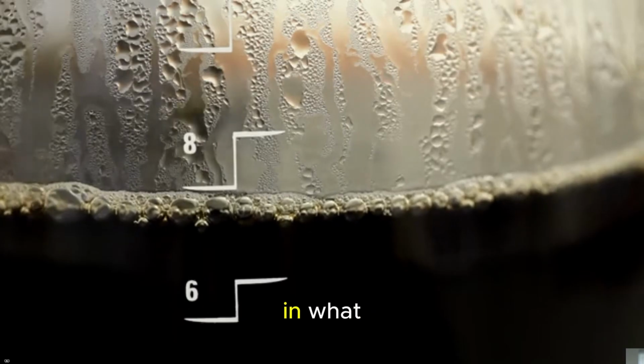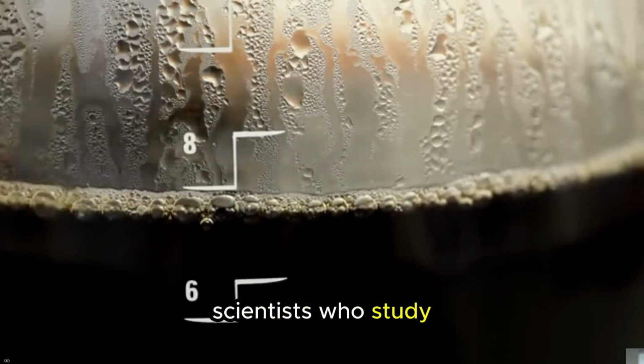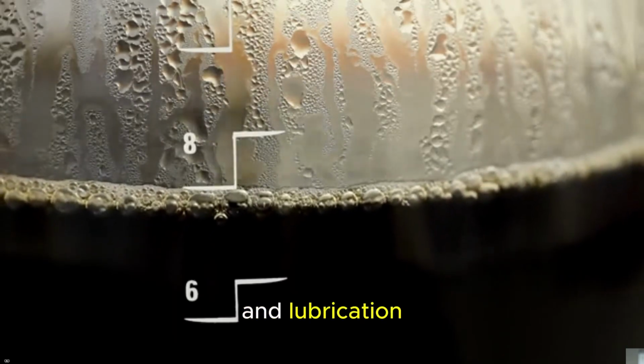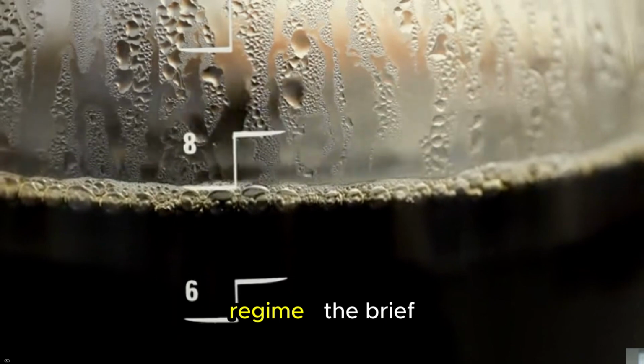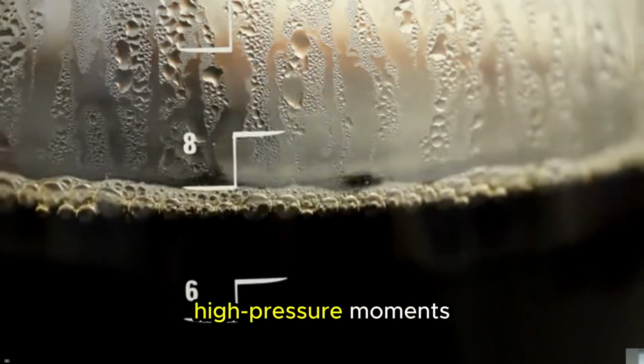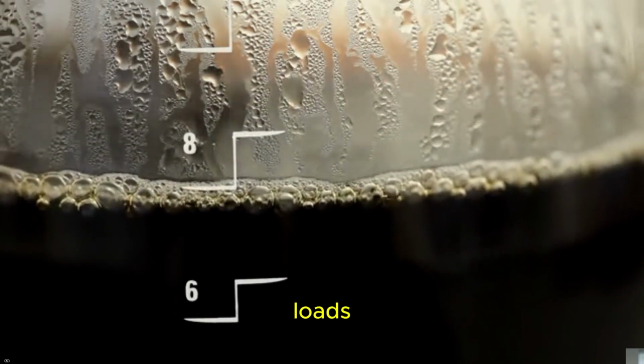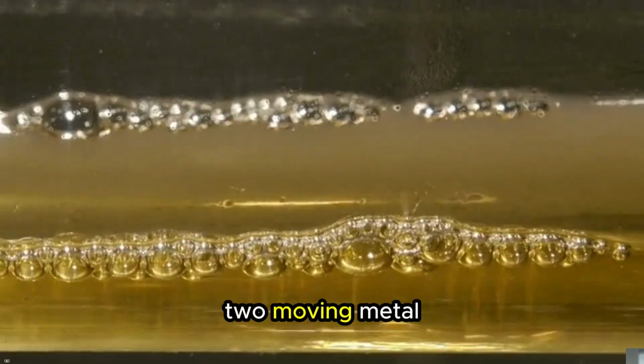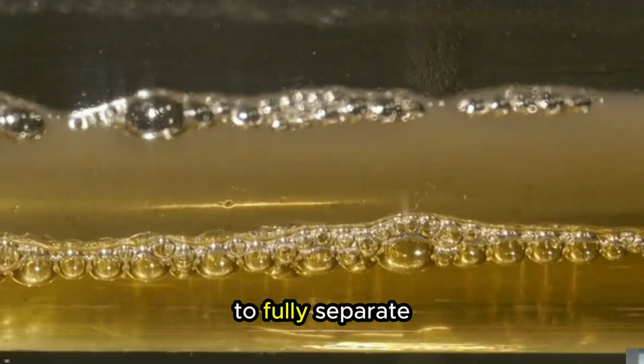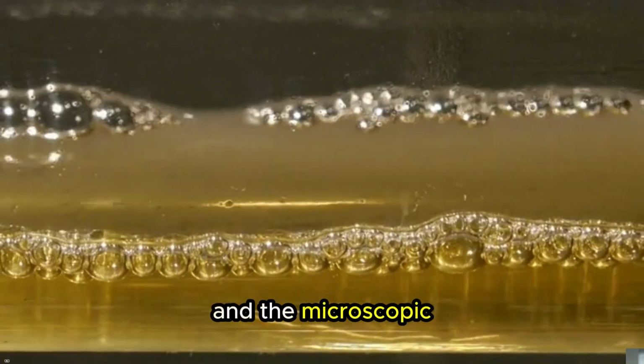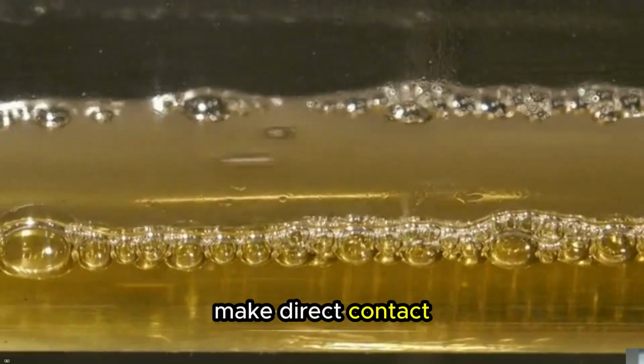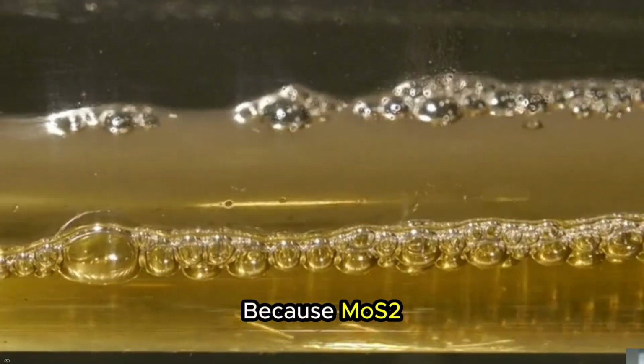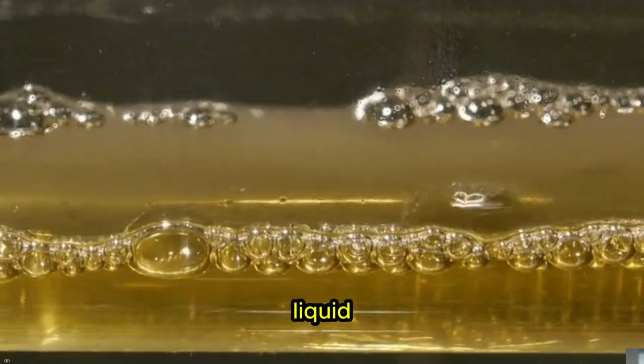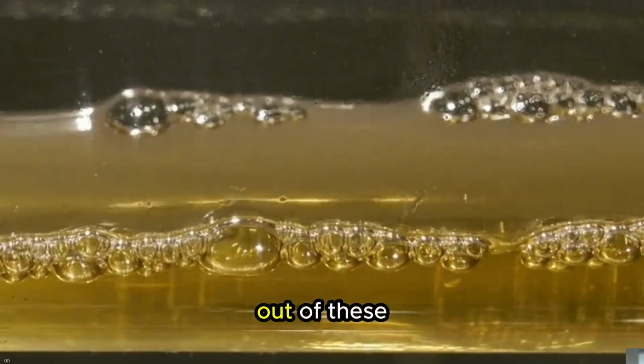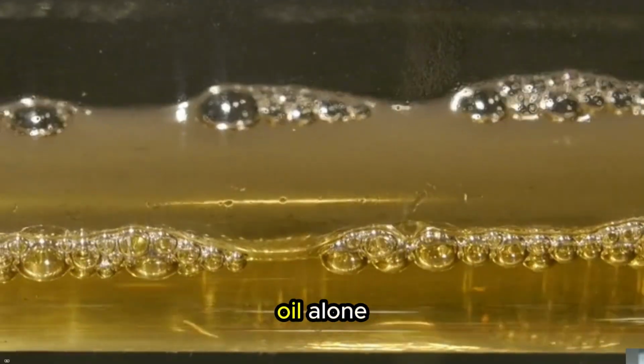This matters most in what tribologists, scientists who study friction, wear, and lubrication, call the boundary lubrication regime. The brief, high-pressure moments, such as cold starts or heavy loads, when the oil film between 2 moving metal surfaces becomes too thin to fully separate them, and the microscopic peaks on each surface make direct contact. Because MoS2 is a solid rather than a liquid, it is far more resistant to being squeezed out of these high-pressure contact zones than oil alone.